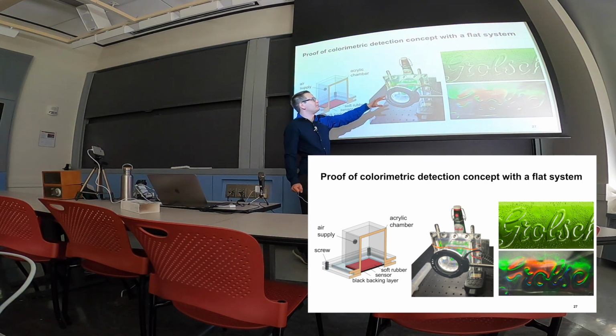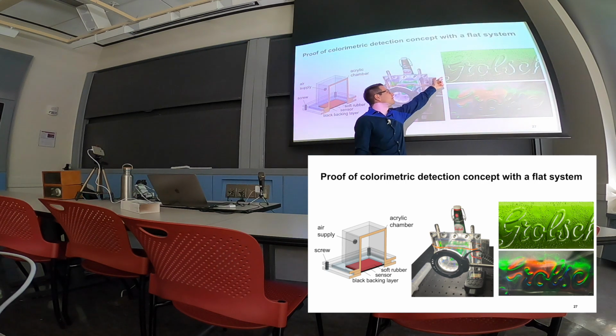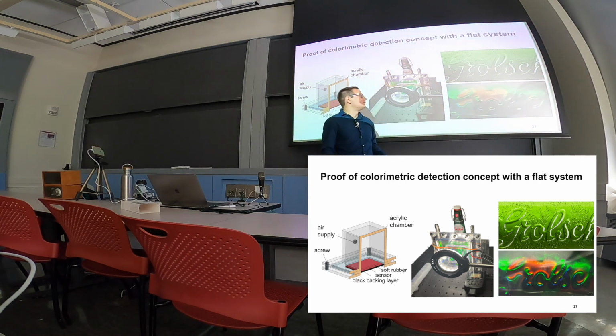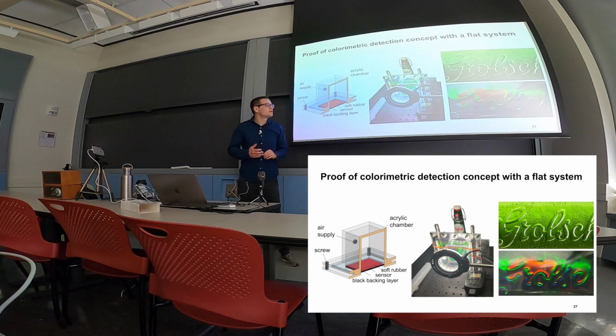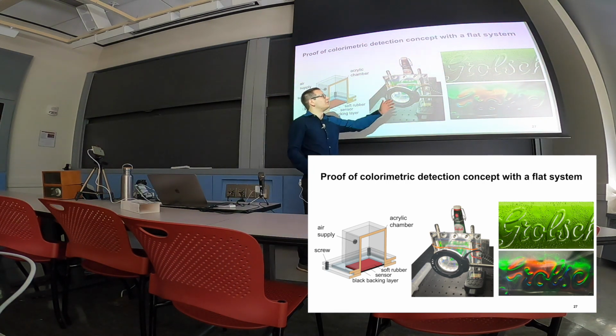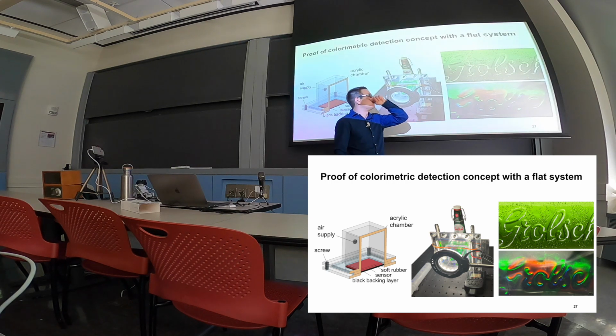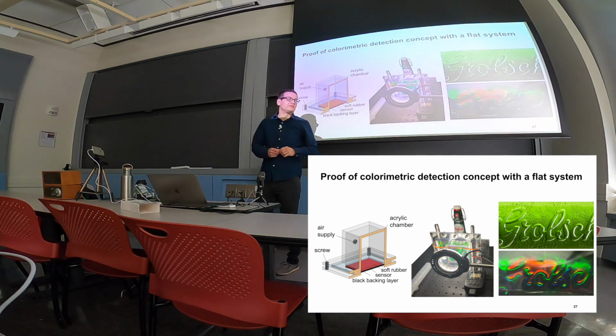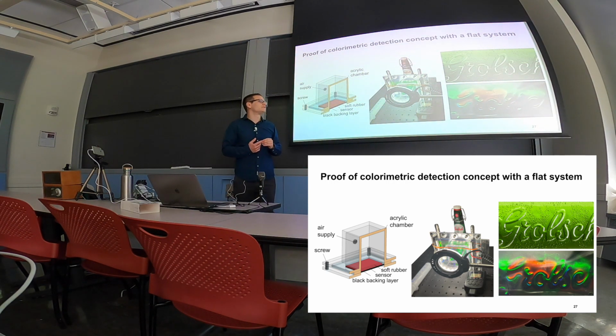And we see once I press that against the texture, I see on the right side the Grolsch logo. This Grolsch logo pops up quite clearly out of that structure, so we have a higher contrast between the background and the logo. And I once again have to mention that the logo that has been photographed over here was taken by a professional photographer, so it would not look like this if I had just taken it inside of our lab.